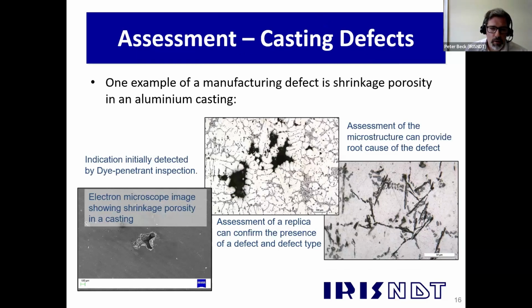We can also look at casting defects as one example. So one issue may be that if you have a defect like this on the surface, then it could be indicative of porosity throughout the casting. That could give you leak sites through the wall thickness, or it could act as sites for corrosion to initiate. So this is an aluminium casting that we had. From a dye penetrant inspection, we initially detected the pores. They're quite difficult to see by the naked eye, so I've actually included an electron image. We were lucky with this that it was actually a failed part, so we were able to cut it up.